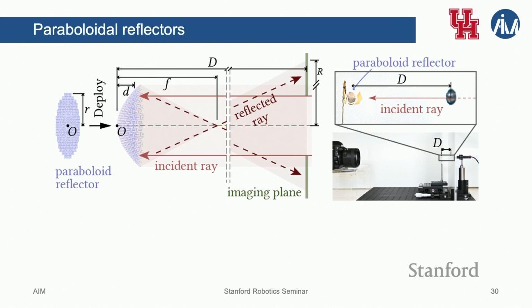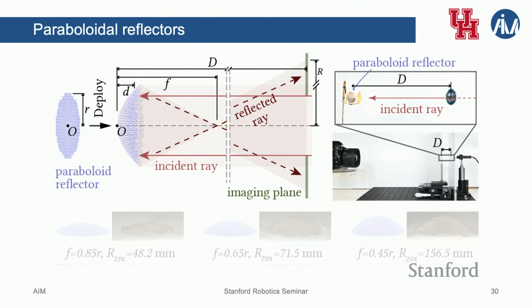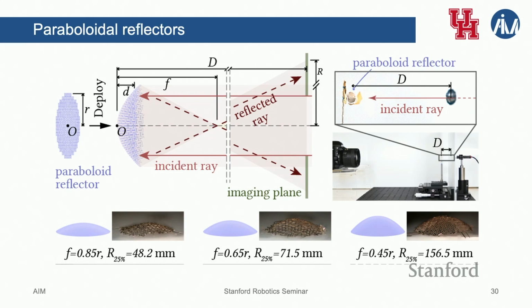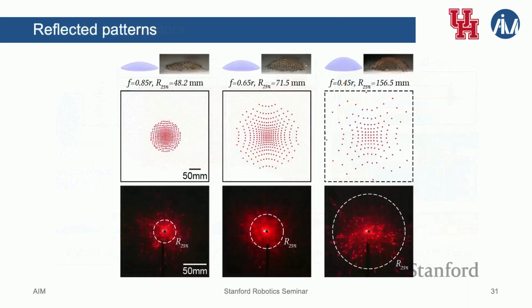The laser rays will reflect, converge at a focal point, and then diverge and hit the imaging plane. And we want to see if the pattern on the imaging plane matches what we expect. So if it does, then we can say the shape that we deployed the flat structure into is correct. And these are the three, we tried 3 different focal lengths, and you can see they're differently curved. They're all parabolic surfaces, just of different curvature. And they pretty much do what we expect them to do, right?